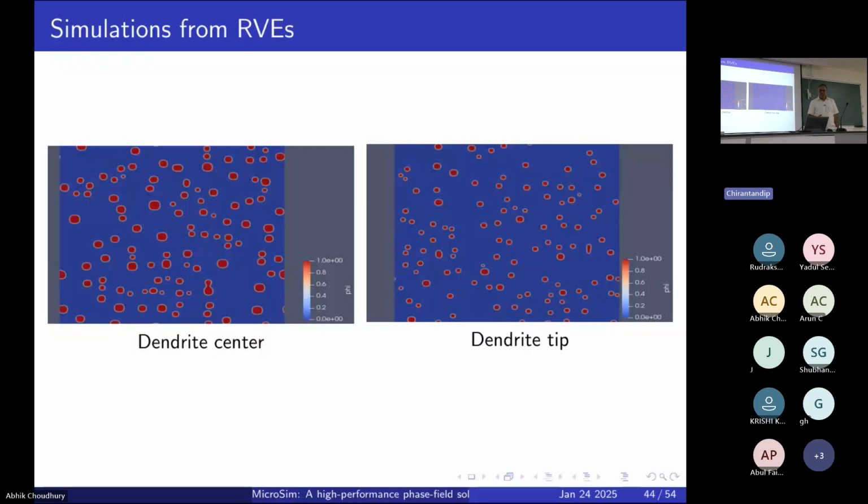Segregation does play a role when it comes to precipitation in superalloys. So no wonder the precipitation heat treatments are so very complex. They actually need to homogenize so that the dendrite formation is removed as much as possible before they go to the precipitation. Here is where again we have done something interesting recently, using 3D printing,